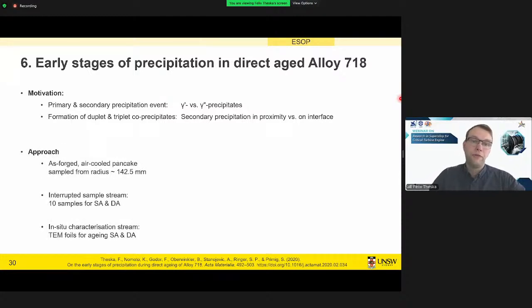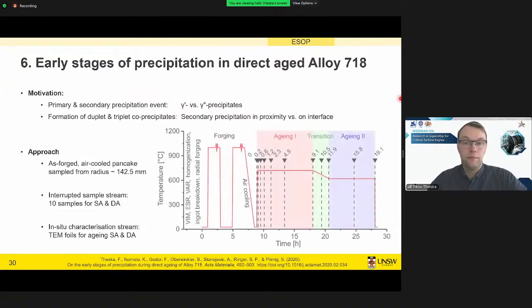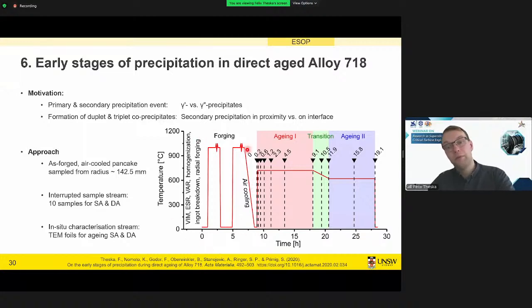And in our approach, we took the same material from an industrially forged, not disc, but an industrially forged material that has been air-cooled, and then created an interrupted direct aging sample stream. You see, this is again our time-temperature profile. The solution annealing is gone, your direct aging, and each of these black arrows marks one sample.